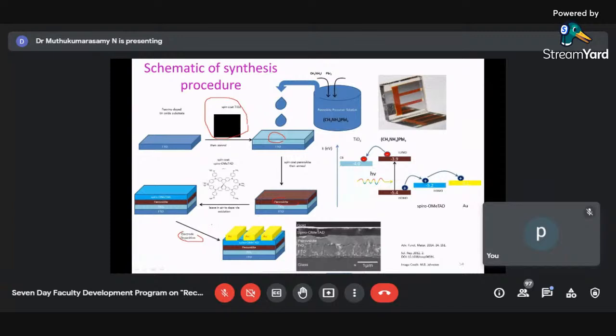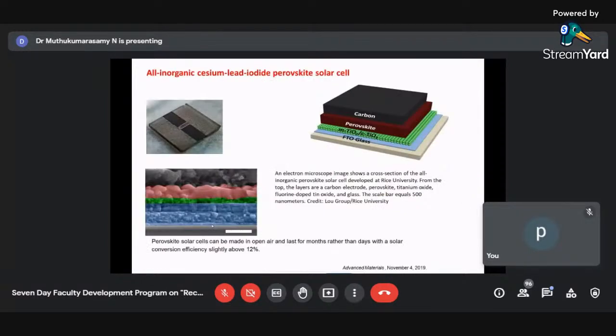So you can see there are 4 layers: glass plate coated with FTO. Then you have your titanium dioxide electron transporting material, then the perovskite material, then you have the hole transporting material spiro. Above that you have your gold, and gold is a grid, because you have to allow light to fall on it. And this is one which they have developed, all inorganic cesium lead iodide perovskite solar cell. They have developed the solar cell without using any organic type of material. So cesium only they have used, and they have fabricated a solar cell. This was by the people from Rice University, and they have reported nearly 12%.